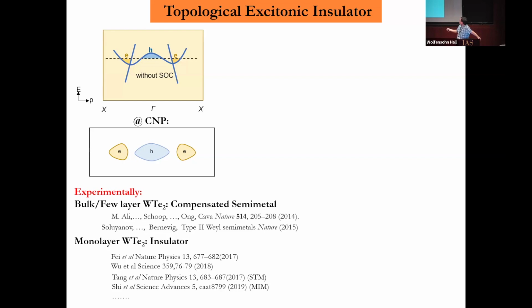Experimentally we do see semimetal behavior in bulk - that's very much confirmed, and it was one of the first things confirmed when this was initially synthesized in the bulk case. It's called a compensated semimetal, meaning you have exactly equal numbers of electrons and holes.